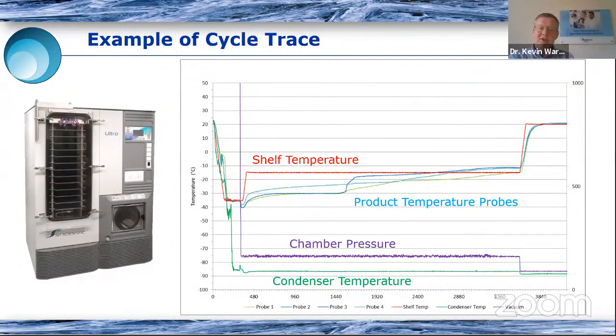So once we've got some basic information about our formulation, we then need to consider how are we going to apply that knowledge when we come to freeze dry that formulation. And so here we have an example of a freeze dryer, and it has a number of shelves, and those stainless steel shelves are controlled in terms of their temperature by a fluid which circulates through the shelves, in this case a low viscosity silicon oil. And therefore, in our freeze drying cycle, we can set the shelf temperature, and we can expect that to be maintained throughout the process. So this is one of our control parameters, and the other control parameter is chamber pressure. So these are the things that we directly control in this freeze dryer.